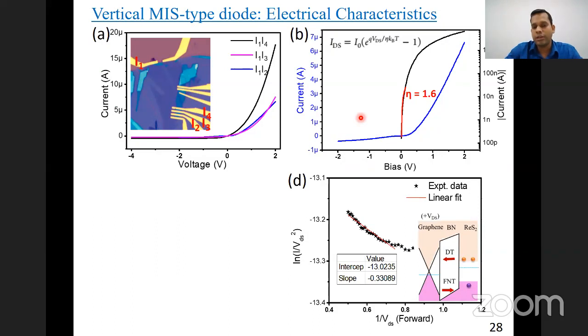And if we do the analysis for the diode, plot them and extract the ideality factor, then we get quite a low value, like 1.6. And for high field strength, that means at a low bias, if we plot this function, the fitting with the Fowler-Nordheim tunneling equation is well fitted. Basically, this FN tunneling takes place for high field strength. So that again confirms that this is a quantum tunneling diode, and this whole process can be temperature independent.